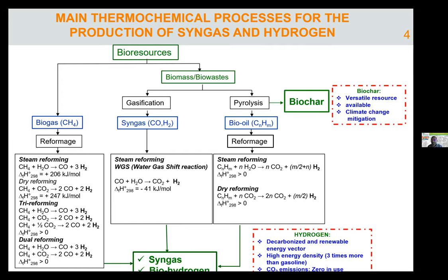And energy density is 3 times higher than gasoline. These are enough arguments, which means with 1 liter of gasoline, I can travel 3 times less distance, for example in transportation, than with the equivalent amount of hydrogen. This makes the difference, even if it comes with other issues that I'm going to address in a couple of minutes. And also the CO2 emissions, since the hydrogen conversion doesn't generate CO2, and it's kind of a zero emission in use. This is very important too.